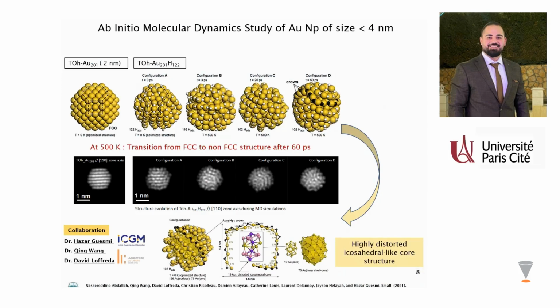So this first study showed that during exposure to hydrogen, gold nanoparticles having a size less than 4 nanometers can be highly reactive and show a complete transition of the crystalline structure during hydrogen adsorption and dissociation processes.